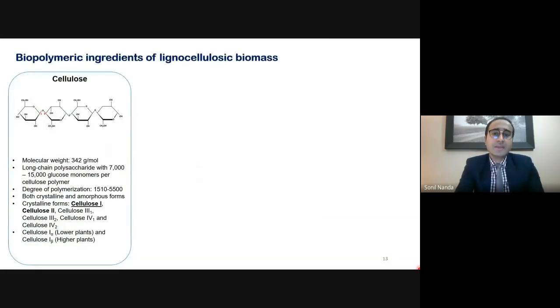Now, coming to cellulose. As I mentioned, cellulose is a long-chain polymer of glucose monomers connected by beta-1,4 glycosidic linkages, van der Waals forces, and hydrogen bonds. Cellulose has a molecular weight of 342 grams per mole, and it is a long-chain polysaccharide containing around 7,000 to 15,000 glucose monomers. But this is subject to vary depending on the source of the precursor, depending on the plant source. And the degree of polymerization of cellulose ranges somewhere between 1,500 to 5,500 typically, but it can go a little up and down. And cellulose occurs in both crystalline and amorphous forms. The crystalline forms of cellulose predominantly found are cellulose 1 and 2. Also, cellulose 3-1, 3-2, 4-1, 4-2 are also available. In the lower plants or the herbaceous or agricultural residues, cellulose 1 alpha is found, whereas in the higher plants or in the long-living trees, cellulose 1 beta is predominantly found.